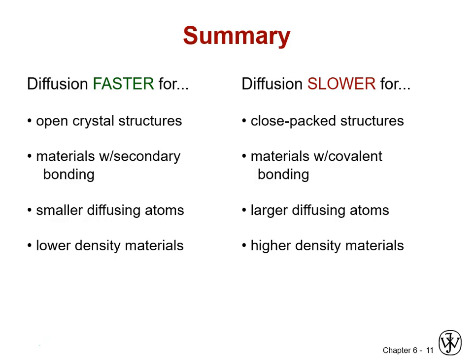One exercise that you might encounter is diffusion rates of different types of gas molecules through polymers. Bigger gas molecules diffuse much more slowly than smaller ones. One of the reasons why hydrogen is a big concern in diffusion. It is actually small enough to diffuse at room temperature through certain metal lattices and cause all kinds of problems, some of which we will touch on in fracture later on.